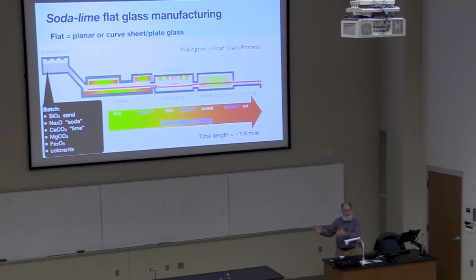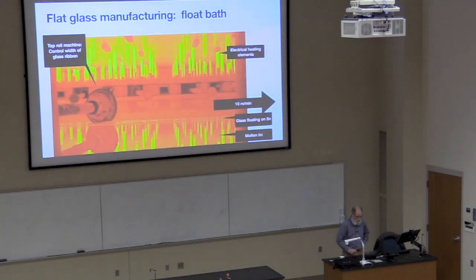And then it goes down the annealing lehr, and you can imagine the glass is 3 meters wide. The outside of the glass would cool faster than the inside, so you've got this big enclosed annealing lehr to keep it cooling uniformly across the width down to the cold end. And then at the bottom end, it's cut into block size. Total length of this glass float line from the furnace to the end is about a quarter mile. So when I was working, we would be working up here and then going down and checking the glass. It was really good exercise. So this is the float glass operation.